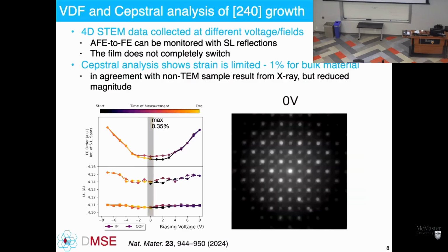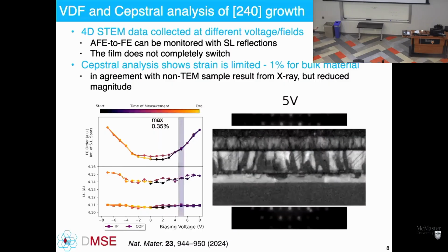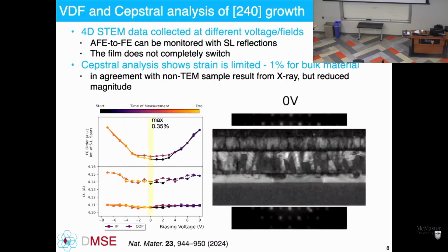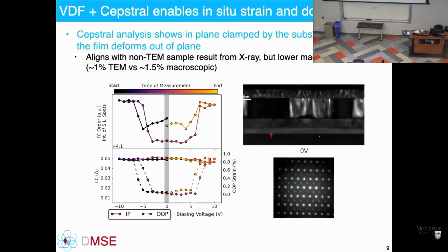the antiferroelectric phase. And that antiferroelectric is showing up as bright white here, with planar defects showing up. And as we apply voltage, you'll see that that largely disappears and comes back when we go to 0 volts, back at the middle. So we can watch these devices in action and understand the response back to their bulk properties.